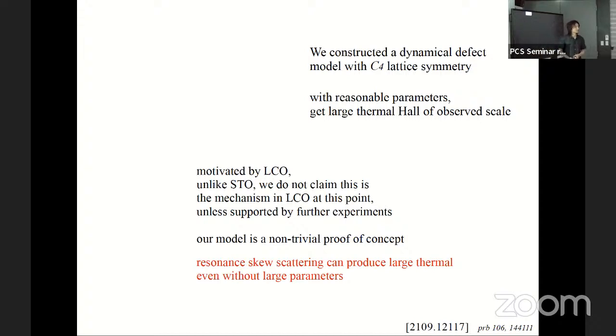And why didn't you consider such resonant effects in the case of the earlier material, STO? It can have them, but it didn't need to, because there's an obvious reason: there is strong scattering from the twin boundary. So it doesn't have to have defects like this. But maybe on the twin boundary there's something like this, because it's speculated by some experiments that on the twin boundary there are indeed some low energy degrees of freedom, but we don't know the details. So this is a proof of concept.